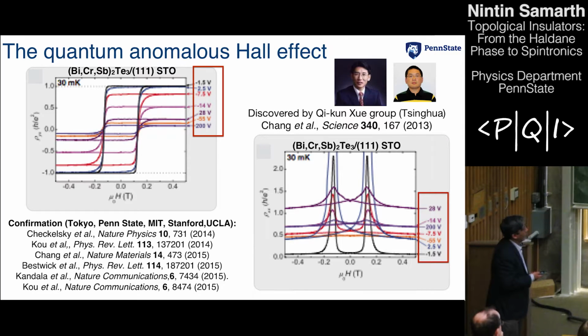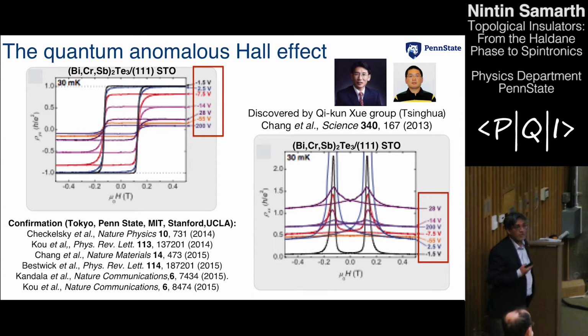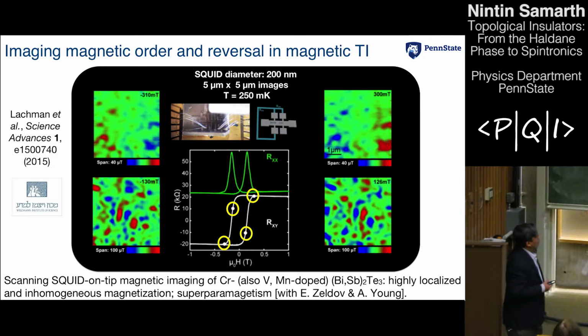And in fact, what they found was that the resistivity of the sample never actually went to 0. It looks like this on the scale, but it's not. It's still sizable. But since this initial paper, which is a seminal paper, it's the seminal discovery of this phenomenon, a number of groups, including mine, have shown that this is indeed reproducible. It's real physics. It's not some accident. And you can make samples that show these properties. And this has come to be known as the quantum anomalous Hall effect, and in many ways is actually the first physical realization of this phenomenon that Haldane predicted. Although, of course, not at all in the form that he envisioned, for somewhat different reasons.